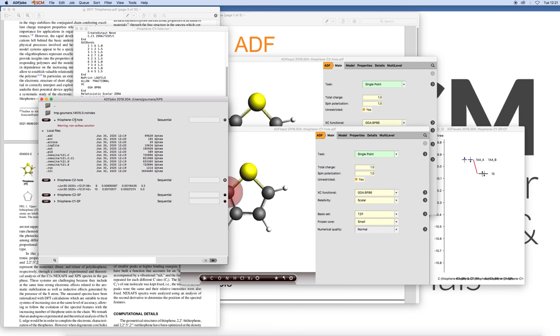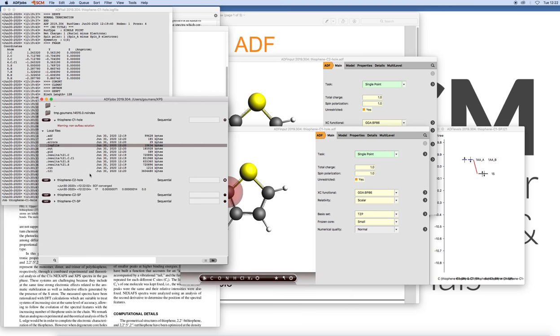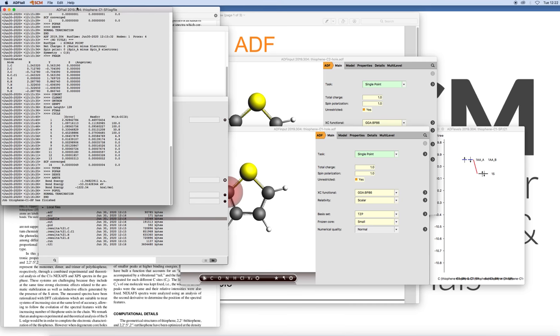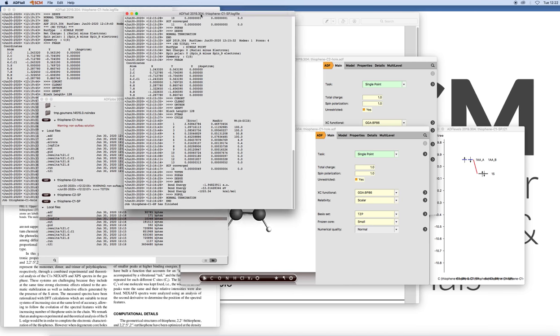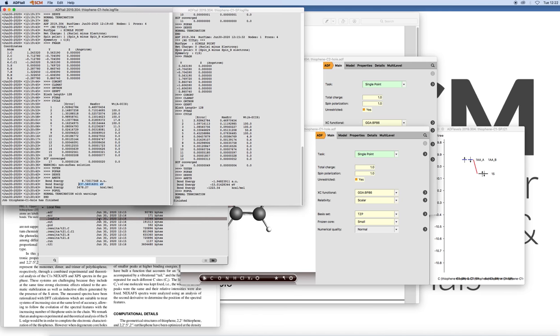Our C1 hole state calculation is finished. We open up the log file, and here in the bottom we can find the bond energy. That is the energy with respect to the fragments, so the neutral fragments that we started with. We do the same for the neutral system. So we click on that arrow there, look at the log file. Then we compare these two values here.